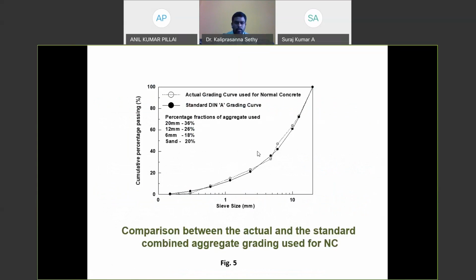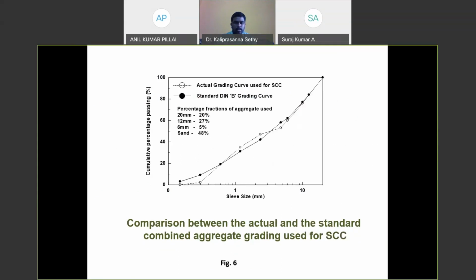So here is the DIN A curve. This is the DIN A standard, and to get a best fit to this DIN A standard, we have taken 36, 26, 18, and 20% of 20, 12, 6, and sand aggregates to develop normal concrete. And for self-compacting concrete, we followed the standard DIN B grading curve, and we decided to take 20% of 20 aggregate, 27 percent, and 48% of these materials for the design of self-compacting concrete.